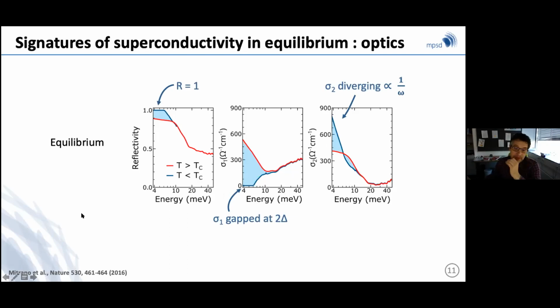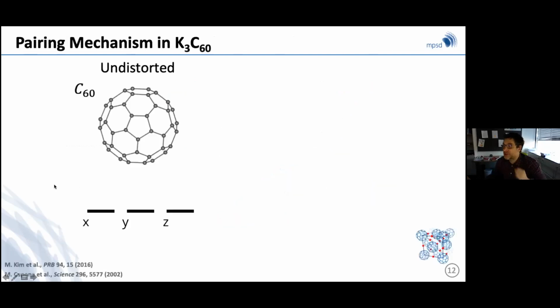What's interesting about this material is that although it's a strongly correlated superconductor, there is some degree of agreement on the microscopic physics that leads to pairing and superconductivity, which is related to the physics of each one of the molecular sites. Remember, each one of these sites occupies one of the FCC sites of the lattice. If I take the undoped, undistorted fullerenes, before I add the potassium, what I have is 3 unoccupied, degenerate lowest unoccupied molecular orbitals. So these are LUMO states, which are degenerate. These are T1u orbitals, but basically they're P orbitals that are pointing in 3 directions along the crystallographic directions.